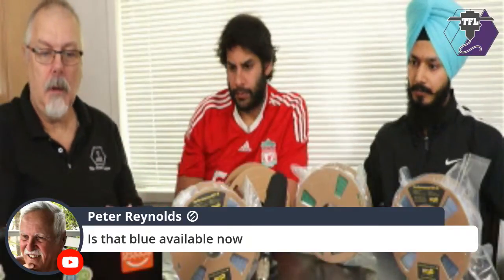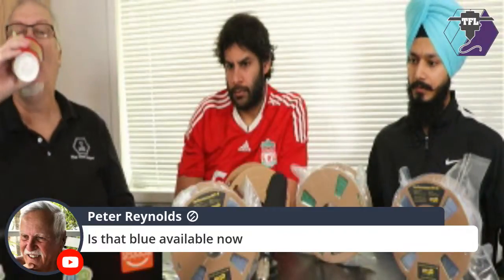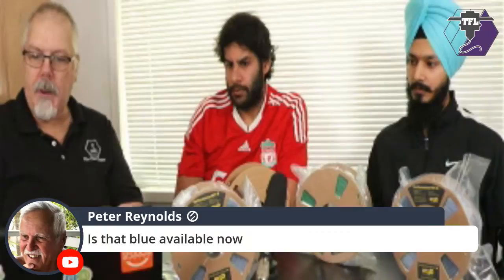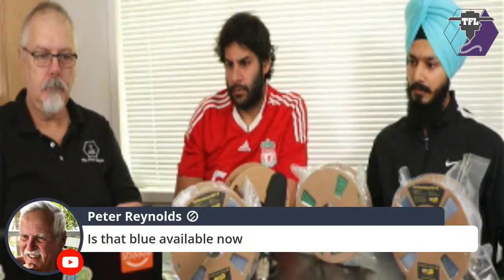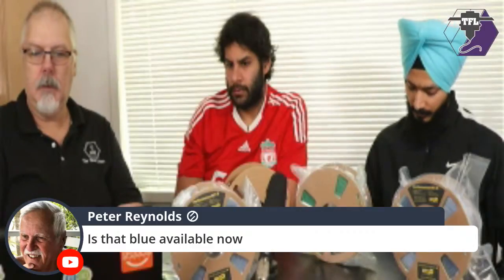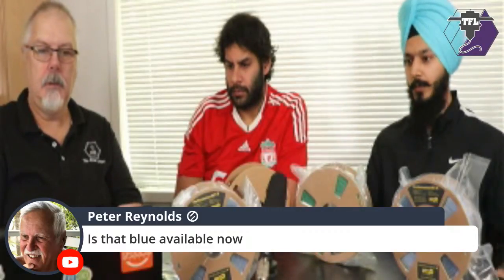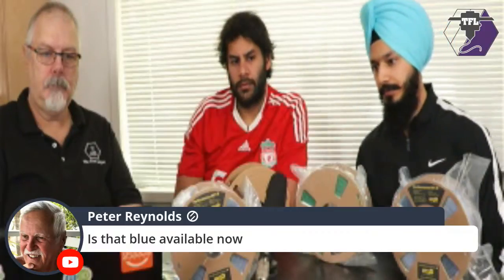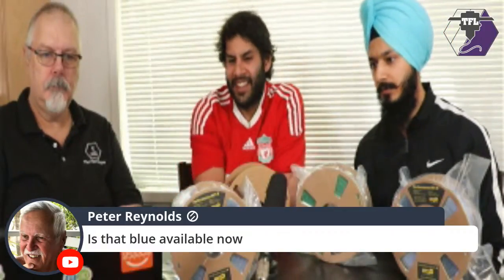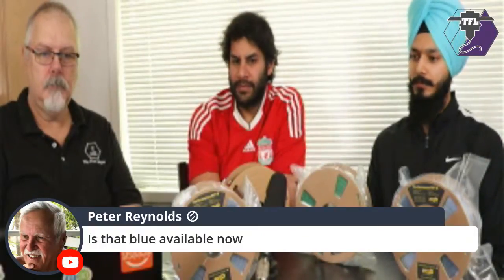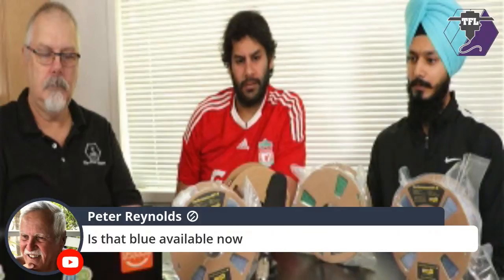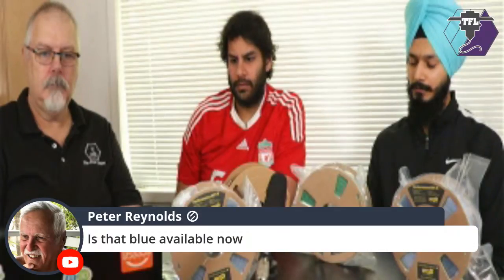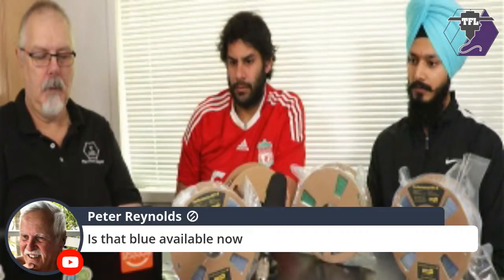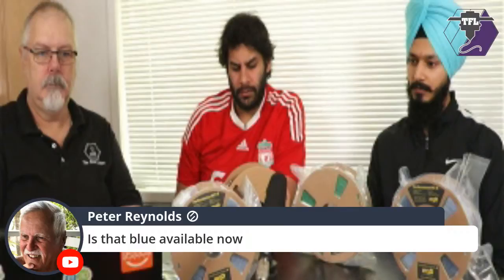But that being said, this is probably the first filament we've been able to work with that we can set a material profile in our slicer and not have to adjust it when we switch reels of the same color. And that's one of the big things that we want to try to push for you guys: cheap PLA can be fine at times. But if you look at your time, if you have to go and recalibrate your settings every time you change a reel, that adds up in time. And I don't know how much your time is worth. But for me, to pay a little bit over the cheapest prices on the market to get that little extra bit of quality, especially for those of you who print in large volumes, it's nice to have a set it and forget it brand. And Matter 3D is really the best I've come across when it comes down to batch consistency.